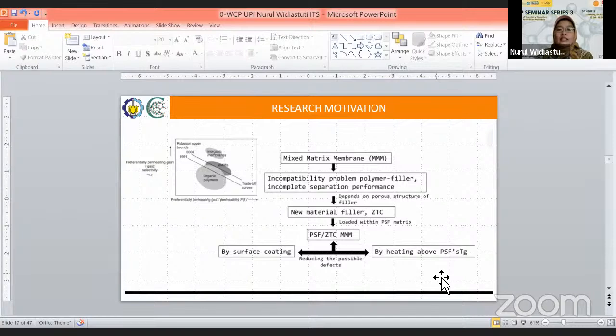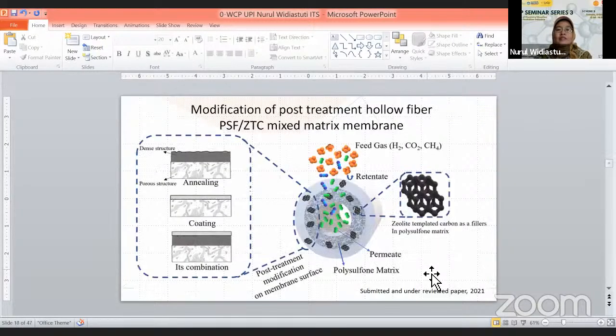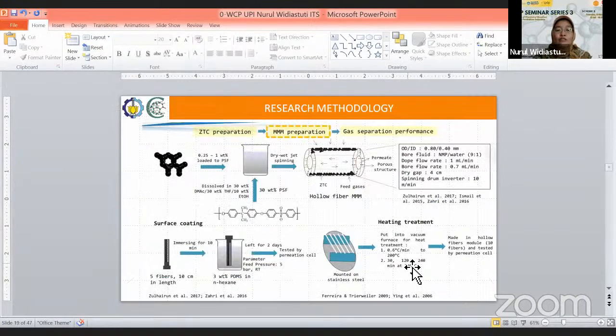So here is the research motivation and the contribution of the research. We propose a new filler material called zeolite templated carbon, and we use it as a filler in mixed matrix membranes with a polysulfone polymer matrix. Then we modify the membranes with surface coating and also with heating above the polysulfone glass transition temperature. Here are illustrations of the post-treatment modification of hollow fiber polysulfone ZTC mixed matrix membranes. And this is the methodology of this research.